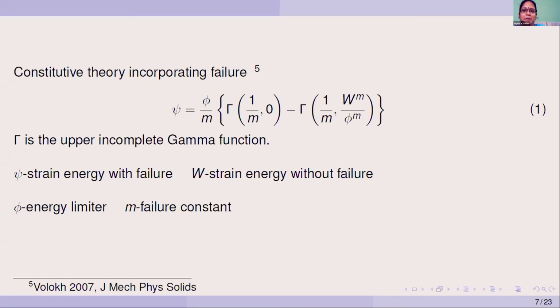M is the parameter which controls the sharpness of the transition. Like if we want a more brittle rupture, we should use a higher value of M. And for a more quasi-brittle rupture, we can reduce the value of M. Okay.